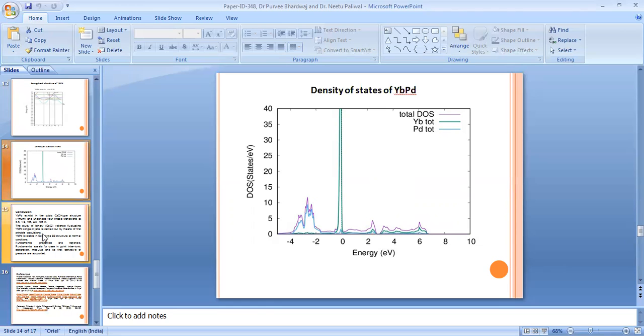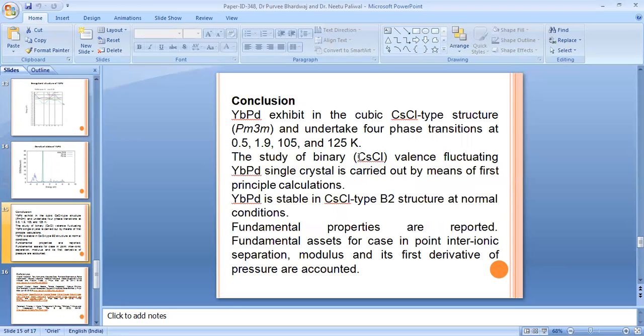The conclusions of this study are the following. YbPd exhibits the cubic CsCl structure, described by Pm3m, and undergoes 4 phase transitions at 0.5, 1.9, 105, and 125 K. The study of binary cesium chloride valency fluctuating YbPd single crystal is carried out by means of first principle calculations. We have used the Wien2k code for this calculation and used the generalized gradient approximation for minimization calculations. YbPd is stable in the cesium chloride B2 type structure at normal conditions.